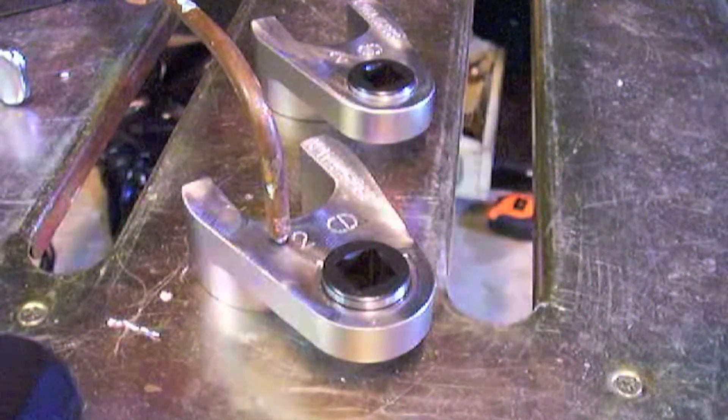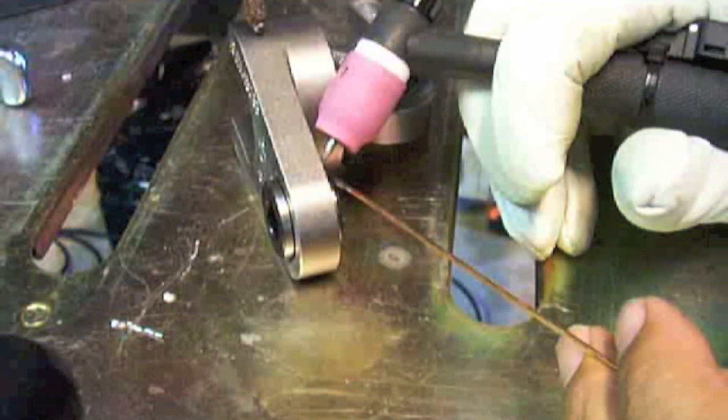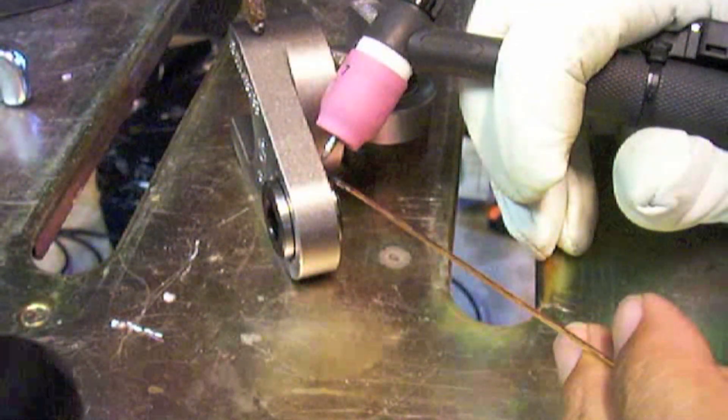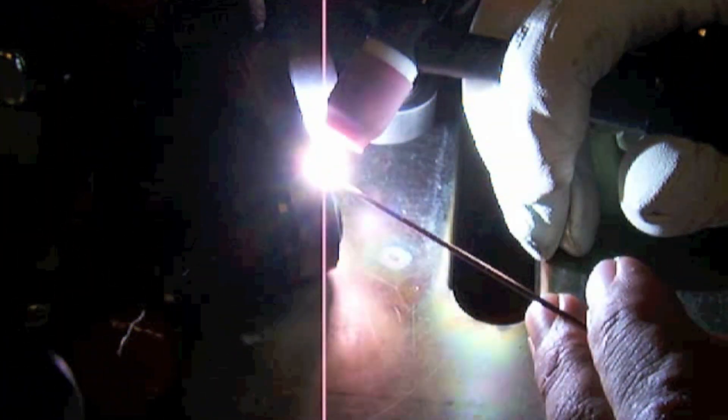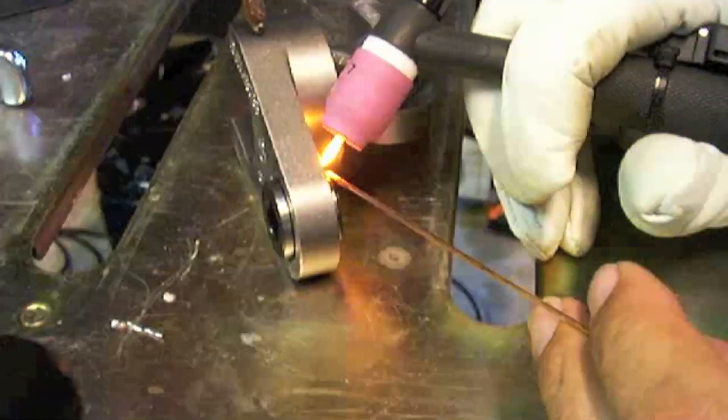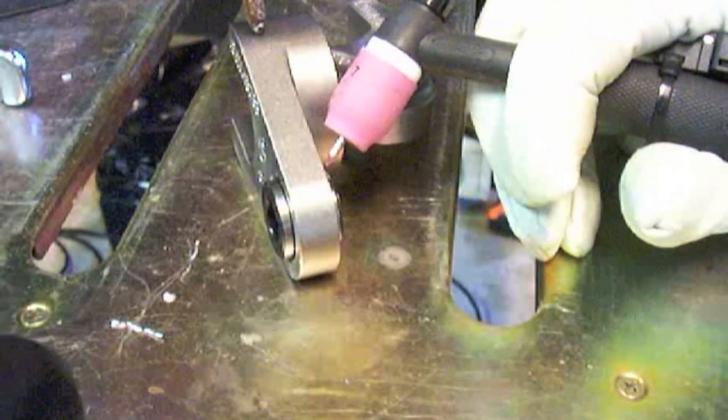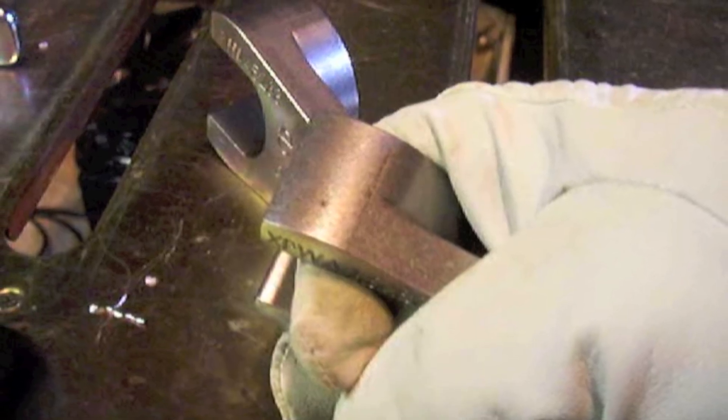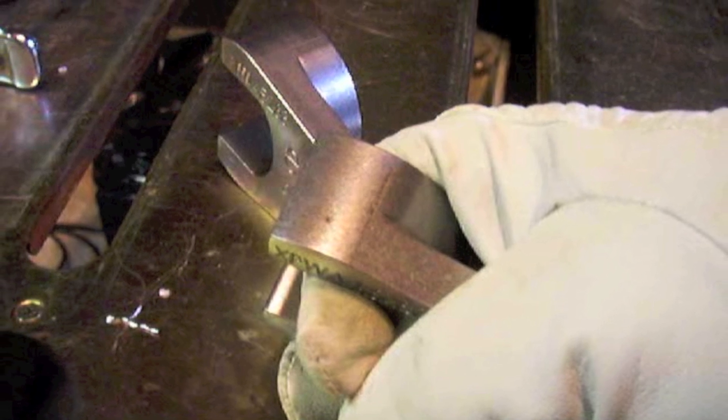Now I'm using this little third hand to hold it. You can see that spark just then—if you rewind it, you can see a little spark come off that third hand. That was a problem. That's putting arc strikes on my parts, and this particular part is a nicely finished polished part that was in a tumbler, and I don't want any arc strikes on it. So to fix that problem...